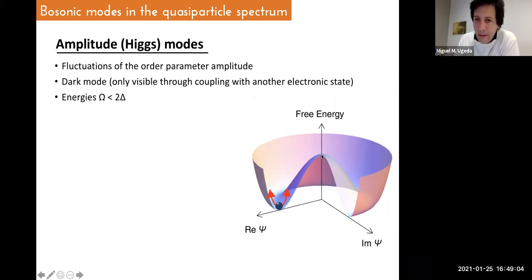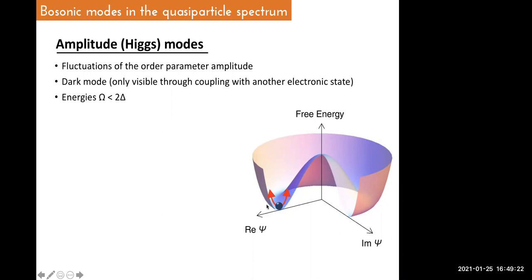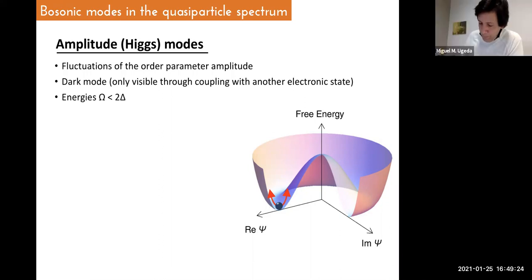This is the free energy of a superconductor: when it becomes superconducting, the symmetry breaks, and the order parameter acquires a very defined value, but this is only true if we take into account fluctuations that may happen. Usually they can be seen through interaction with quasiparticles. However, in superconductivity, these modes are dark modes, meaning that they cannot be observed.